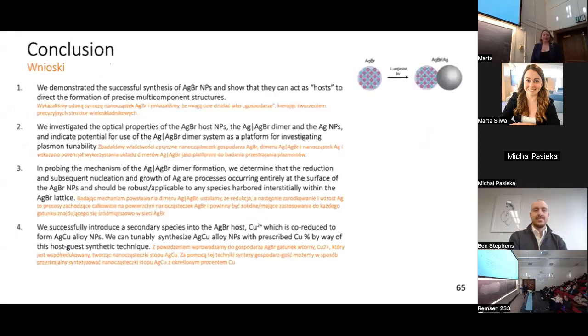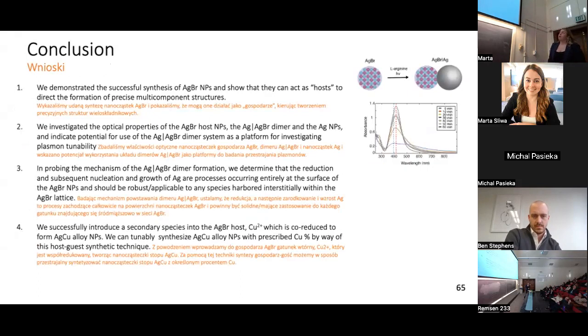So now to recap and wrap up all that I talked about today. I started this talk by showing you that we were able to successfully synthesize silver-silver bromide dimer nanoparticles by way of a silver bromide host intermediate. We then talked about the optical properties of the host nanoparticles, the dimers, and the silver nanoparticles that we're able to yield, and talked about how we could use them as a platform for investigating further plasmon tunability and manipulation.